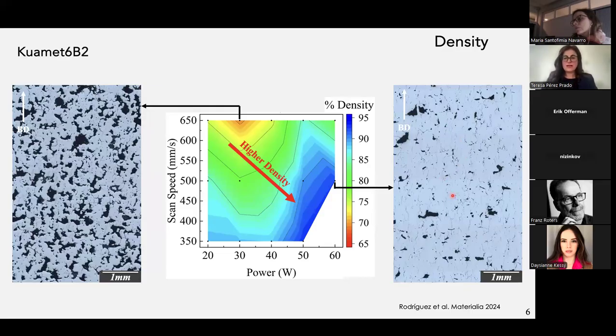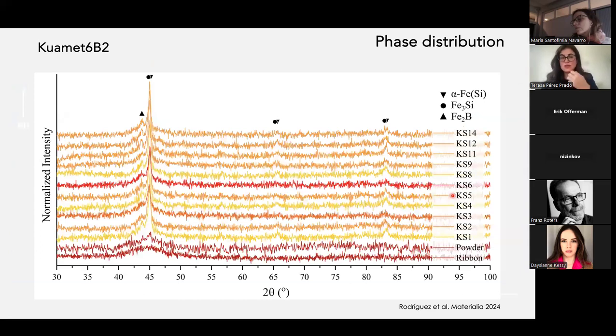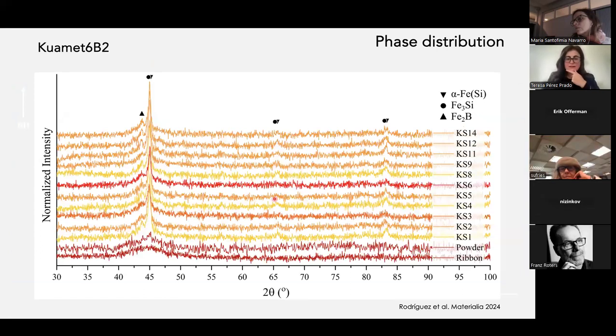Let us see what happens with the phase distribution, with the amorphous fraction. Here I just put all this X-ray diffraction together. We first got a qualitative view of the phase distribution by X-ray diffraction. The only important thing here to look at is the first one at the bottom. This corresponds to a melt spun ribbon of the same composition, Kuamet6B2. We know that by melt spinning, we can produce a fully amorphous material. And the signature of this fully amorphous material is this very wide halo here at 45 degrees.